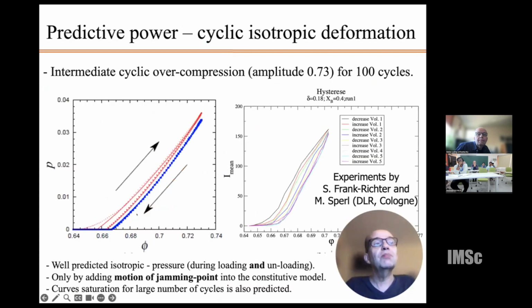Now, on the left you see pressure, some of the data. The points are particle simulations, the lines are the continuum theory from 2016, actually. We had a quasi-static continuum theory at that time, which worked pretty well. And the right data are experimental data, soft hydrogel particles, which confirm the loading and unloading jamming density is not the same.